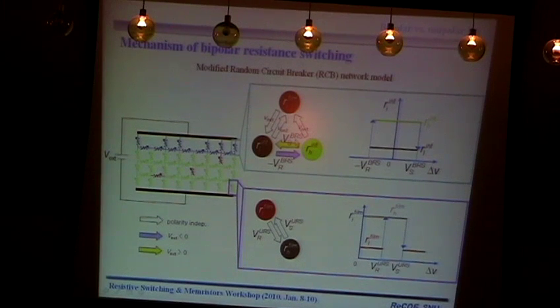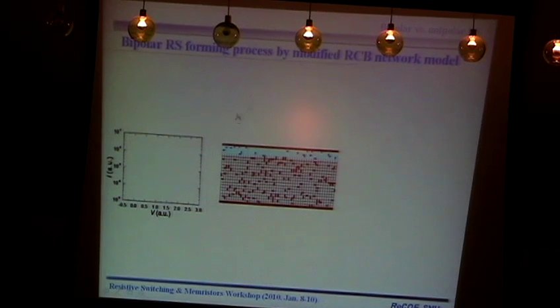And so in here, there's at least 5 switching rules we have to show in detail. But I think the most important switching rules is these two states, between these two insulating states. And we assume that this has polarity dependence. So that the positive polarity is switching one way, and the negative polarity is switching the other way. So with this very simple rule, we perform the simulation again. So we assume that out of this 20 layer, first 3 or 4 layers become in the surface state. And then we perform the simulation.